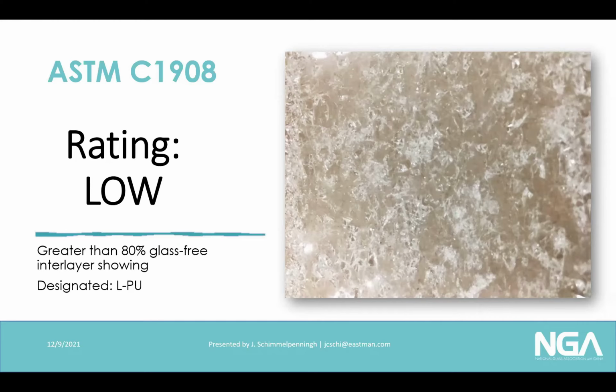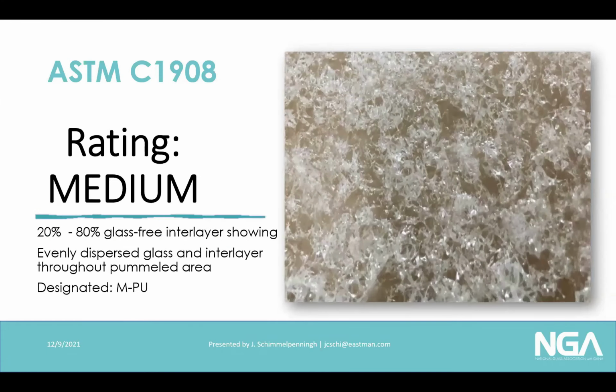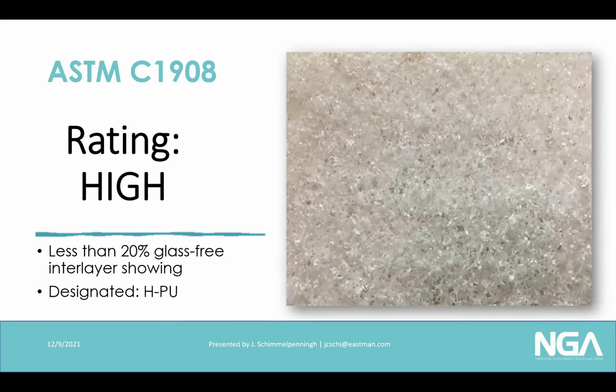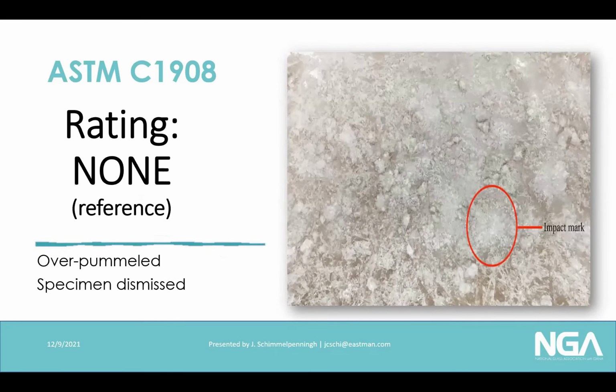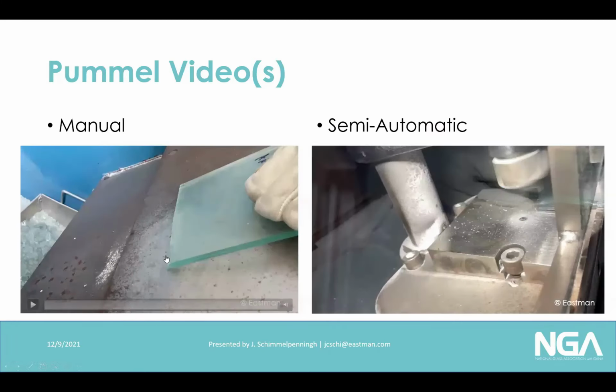It is on a piece of cardboard, and you're actually seeing the brown cardboard below the sample. This is a medium rating, so somewhere between 20 and 80% of the interlayer is covered with glass. And then this is a high rating, meaning less than 20% of the interlayer is showing. Okay. This is a non-rating. Just quickly, this is the pummel method. This is a manual method.